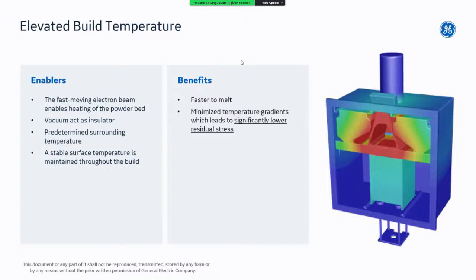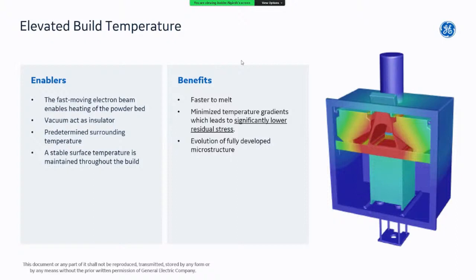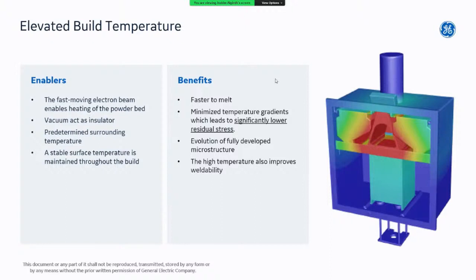Having an elevated surrounding temperature minimizes — and for some materials completely eliminates — residual stresses in the material. When parts come out of the machine, there is no need for post-heat treatment to remove residual stresses built up during the process. You are also able to control the microstructure to achieve a fully developed microstructure depending on the build temperature setup, and of course elevated temperature improves the weldability of some hard-to-weld materials, as we will discuss later.